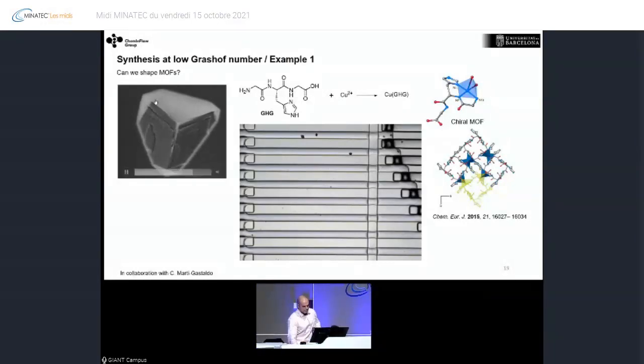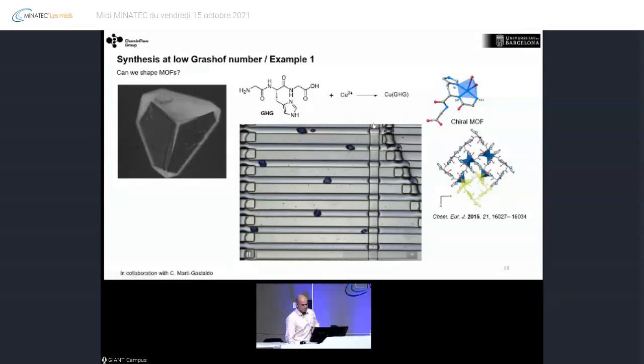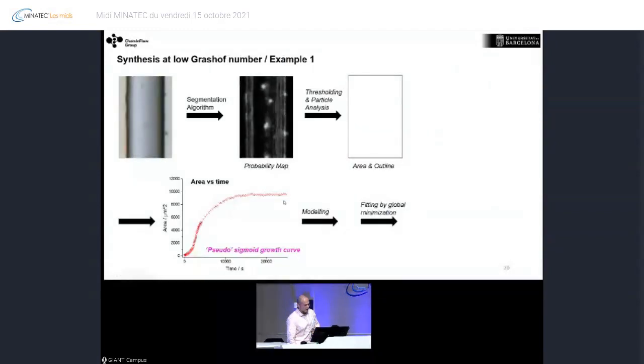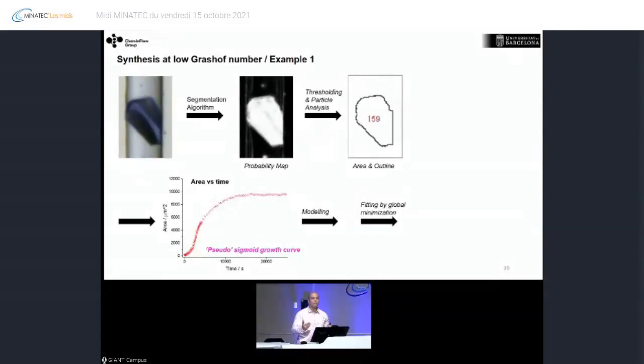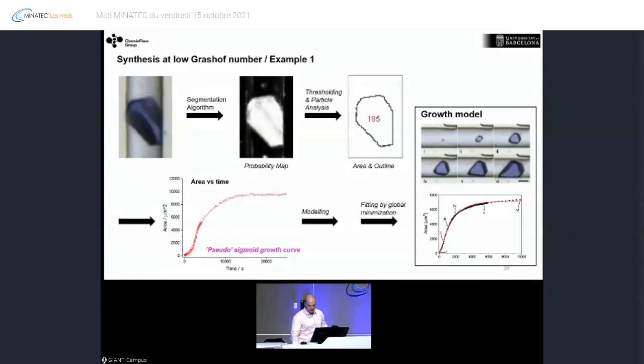So the idea was, again, now to use this peptide-based MOF and do the synthesis in these microfluidic devices that I've shown before. And what you can see here is that we can see perfectly how these MOF crystals are growing. But not only that, via a segmentation algorithm, we can follow the growth and study the kinetics of the growth. We also did a mathematical model that allows us to model the data that we are observing experimentally. And as you see, our model fits quite well to the kinetics of the growth.